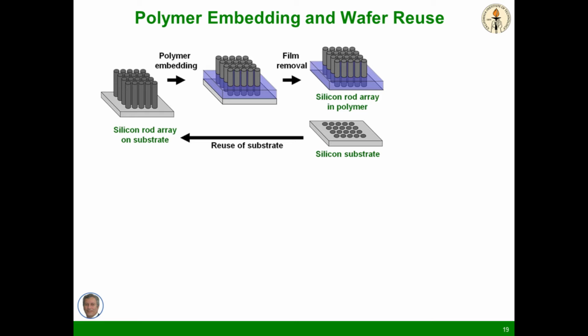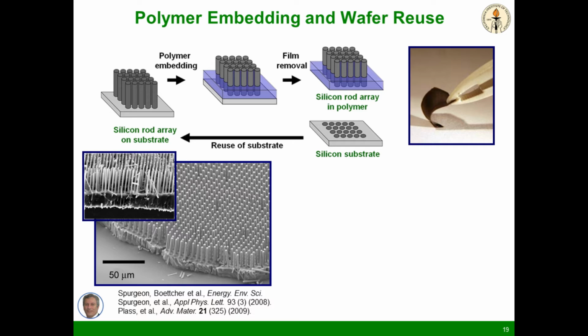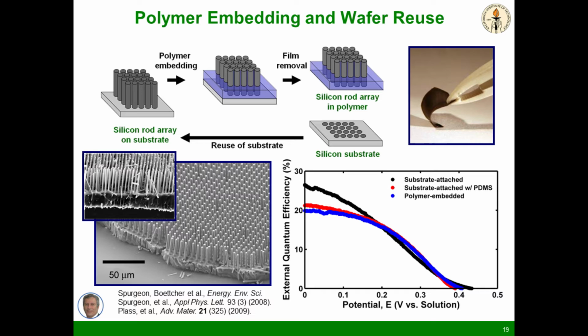And furthermore, as you see down below, it's not necessary that we fully embed the entire rod array with a polymer. We can only embed the bottom parts, or we can embed the bottom and then the middle with something else, and then sacrificially dissolve the bottom after we flip it over and move that polymer up and down in the height to help us make essentially 3D electronics. Now, in addition to that, we can do this with materials other than RTV, fish tank goop. And then we use those materials that conduct protons or hydroxide ions as made in fuel cells as the membrane to really build up a piece that looks like one of our target materials.